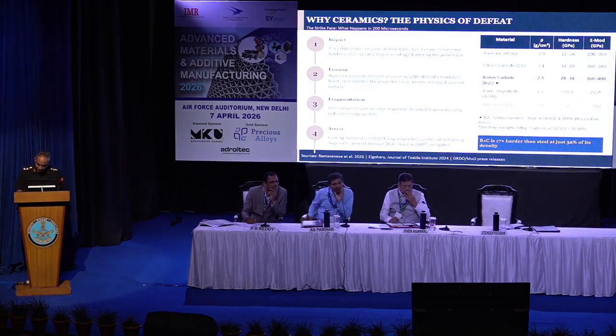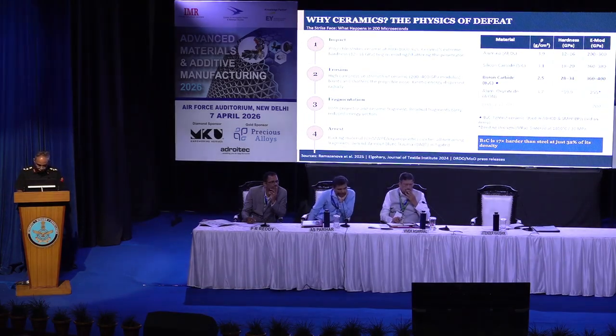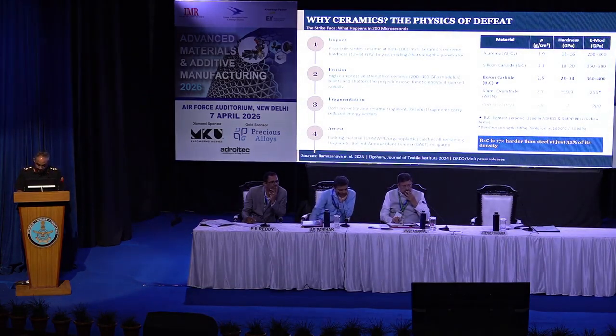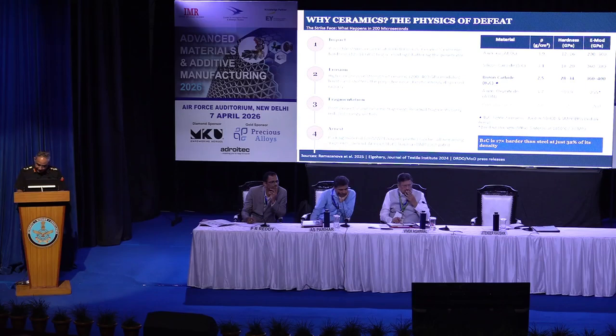Erosion. The elastic modulus of boron carbide, 360 to 400 gigapascal, transmits the impulse radially, dispersing kinetic energy in a cone. The projectile nose is blunted and shattered.